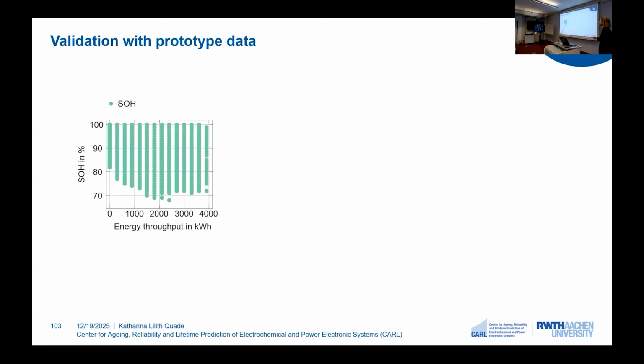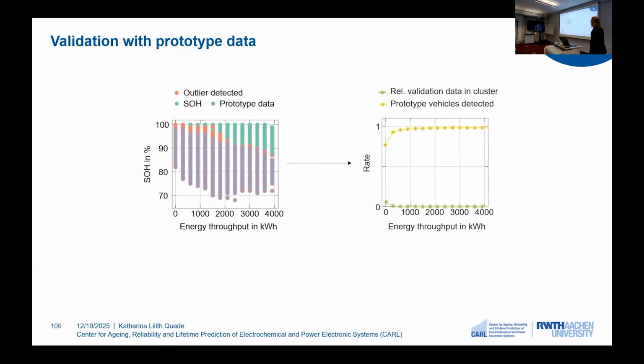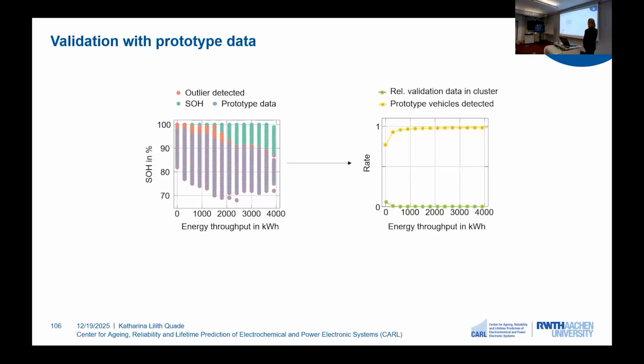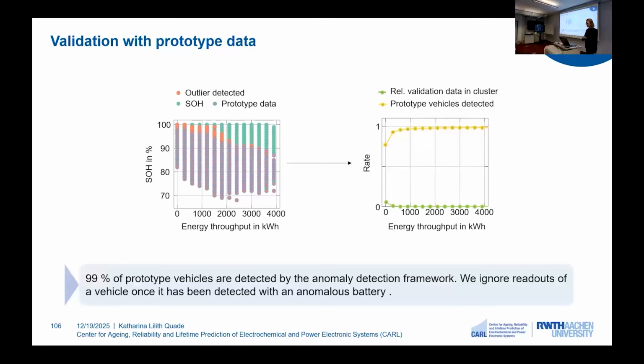Here you can see the resulting clusters. If you can remember, we have a cluster of 300 kilowatt hours. This is why this looks so discrete here. We can now also include the prototype data, as you can see here by the purple circle. We can now use our statistical modeling to analyze how many outliers we have detected. Here on the right-hand side, you can see the detection rate in yellow, and we can see that in total we achieve a detection rate of 99%.